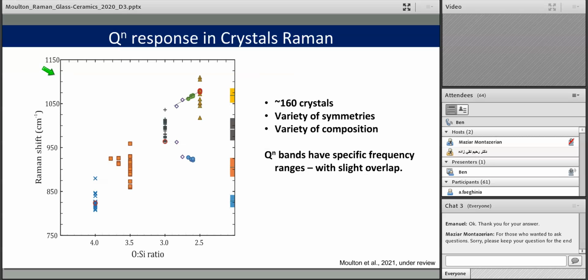I have recently redone this for all 160 different crystal spectra. This is work that's currently under review. And these crystals have a large variety of symmetries and composition. And despite the potential for total chaos in the vibrational modes, we actually see quite consistent ranges here, plotted as a function of their oxygen to silicon ratio. So 4 minus NBO will be Q0, Q1, Q2, Q3 here.